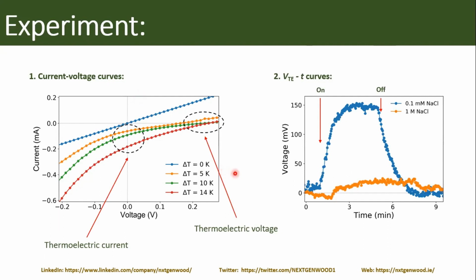Here you can clearly see that this is exactly the same experiment, everything the same except for the electrolyte concentration. So this is a 1 molar solution, and this is a 0.1 millimolar solution. For the same temperature difference, for the same everything, we have quite significant enhancement in terms of thermoelectric voltage.